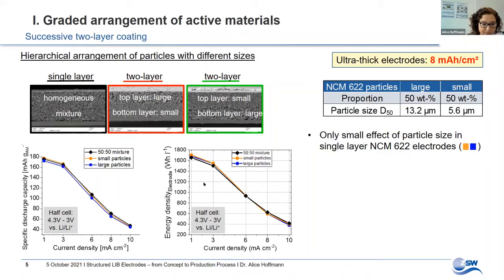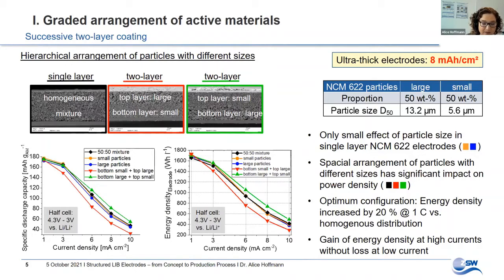And as you can see, in a single layer arrangement, the applied material samples do not show a considerable influence of particle size on rate capability. However, in a two-layer arrangement, we observe a large decrease or increase of material utilization and thus power density, depending on the order of layers. With the large particles near the current collector and the small particles near the separator, shown in green, the energy density of the electrode is increased by 20% at a discharge rate of 1C without a loss at low current density.